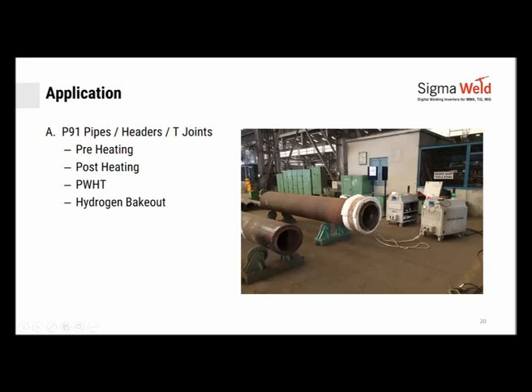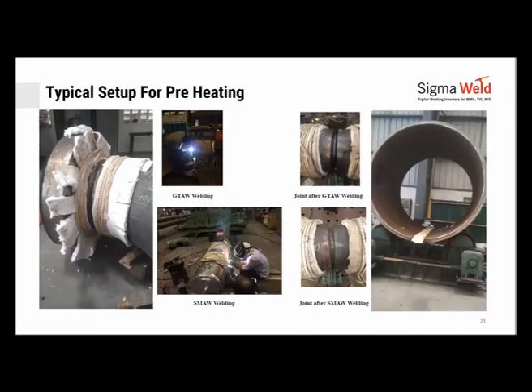You could see the equipment here, the coil being wound on the edge of the header, and once switched on, the heating is on, and it will take the temperature to the level desired. This is a typical setup for preheating, where you could set up the job like this. This is a huge elbow and flange. Here you have to preheat up to 250 degrees. Thicknesses are about 70 mm or so.